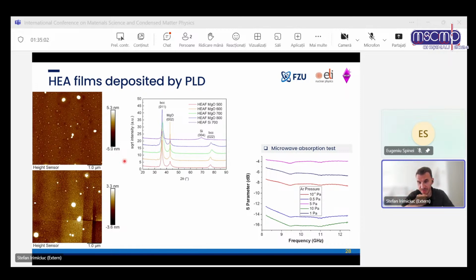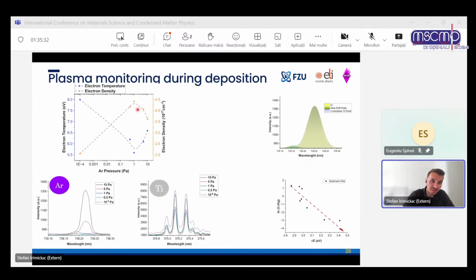to put it in the words of the specialist that we gave them to, he didn't expect to see such a big difference between the films. More importantly, he didn't expect to see such a difference between films produced in such a close range of pressures. But when we looked at the variation of the values, they are really consistent with what we saw here. I'll go back 2 slides, and there is an inflection point around 1 to 5 Pascal, where it seems like even this time the properties and the behavior of the films in the microwave spectra change.